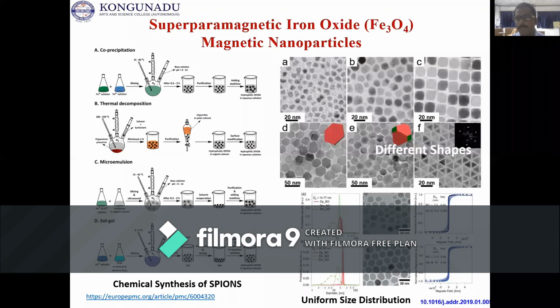And sir, what can be the reason, except for contamination, that we lose magnetism in the hysteresis loop, where you don't get a proper hysteresis loop, even if your material is a superparamagnetic material? Actually, the instability of the spin is the reason for superparamagnetism. When you think about a ferromagnetic hysteresis loop, when you apply a magnetic field to a ferromagnetic material, the initial curve will grow and come to the saturation point of magnetism, and then you reverse the magnetic field.